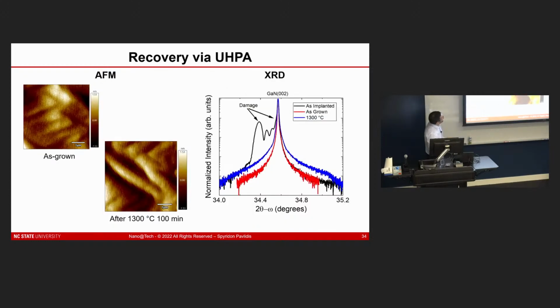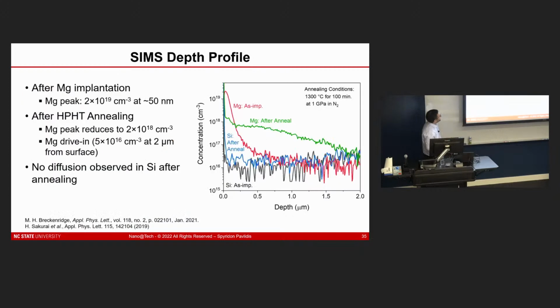This is some materials analysis on these structures that we did along with Zlatko and Ramon. Importantly, I mentioned I don't want the surface to decompose. You can see here AFM morphology and roughness is similar before and after that anneal. So we're holding the material together. And if you look at XRD as well, you can see that when you do the implantation and do the XRD directly afterwards, you have these peaks that are indicative of damage in the crystal, but after the high pressure anneal, you're able to remove those peaks and return back to the high quality GaN as well.